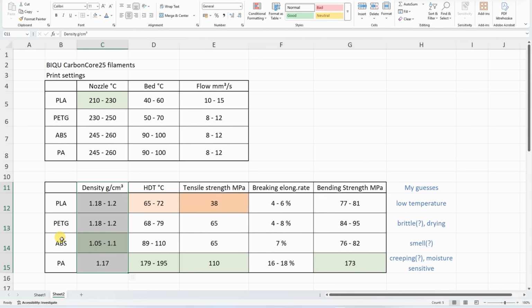First we can see the density, and ABS is the lightest. Heat deflection temperature, huge difference of course between the PLA and the nylon. Now this is a higher value compared to the average PLA, and this is my experience too, that the carbon fibers always increase this heat deflection temperature a little bit. Tensile strength. Now in this table the PLA is the weakest and the nylon is the strongest. My experience is different. PLA is actually quite a strong material with a higher tensile strength. Maybe these carbon fibers will reduce it, I don't know, but it will be measured too.